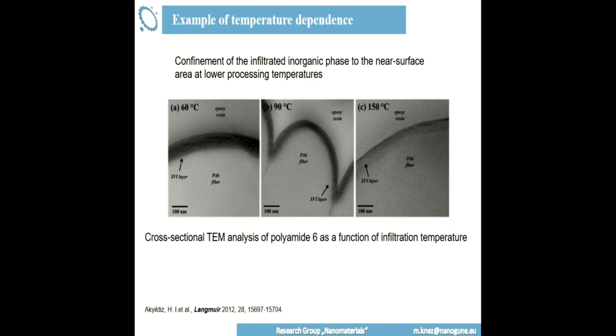But if you do it, you can really have a subsurface growth there. That means the polymer will absorb precursors and you will have a growth inside of the polymer. That means your precursor molecules, if you treat the polymer, will, in most of the cases, grow not only on top but also inside. And this is some work from North Carolina. I think Jesse knows that work very well.